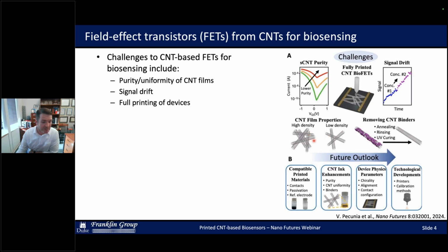There's patchy density that can occur depending on the printing technique, therefore compromising uniformity. There are issues with respect to the residual presence of binders or other molecular species that came through in the solution phase processing of the nanotubes.